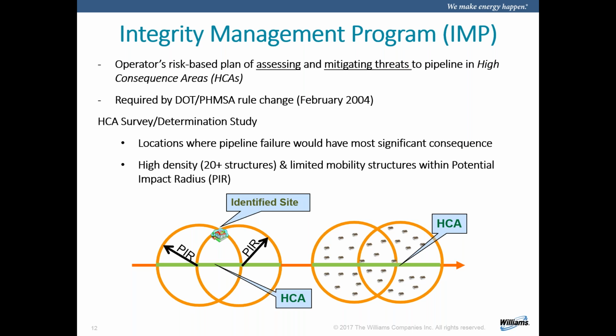If for whatever reason we did not test the pipe high enough when we installed it during original construction, and we needed a higher test, then absolutely we would go in there and perform another hydrostatic test to achieve the appropriate level. And if the pipe is not designed to achieve that level, then we would replace the pipe so that we'd have higher thickness, higher grade steel in the ground so that we could achieve that pressure.